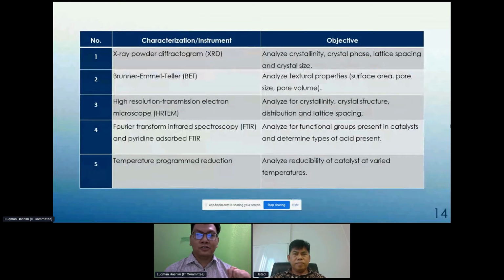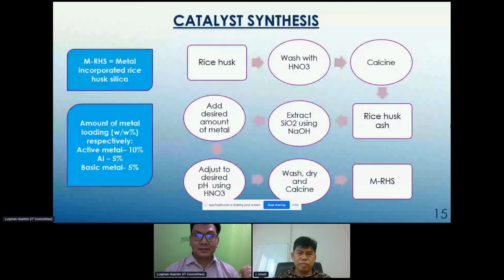Okay, now we are moving on to the characterizations. These are the characterizations that I have used for my catalyst. I will explain them when the time comes. And I will also now briefly explain the catalyst synthesis process. Basically, from the rice husk, we wash it with nitric acid, we calcine it, and then we get the rice husk ash, and then we extract the silica itself using sodium hydroxide, getting a basic solution. And then into the basic solution, we introduce our three metals, the transition metals, the active metals, the aluminium, and the basic oxide, magnesium oxide.